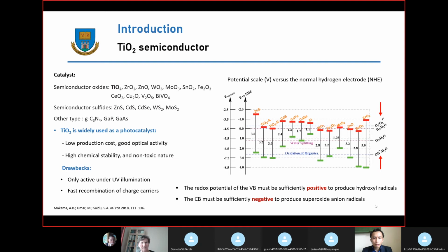There are some types of semiconductors for this purpose, but it should be taken into consideration that the band edge position should be suitable to produce both hydroxyl radical and superoxide anion radical. So in this case, titanium dioxide is a good photocatalyst. Besides that, this material is also easy to obtain, relatively low cost, highly stable and non-toxic in the environment. However, this material can only be activated under UV illumination due to its wide bandgap energy. And in addition, the fast recombination of the charge carriers is also a disadvantage of this material.